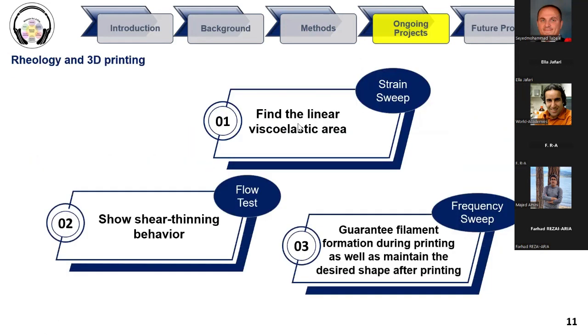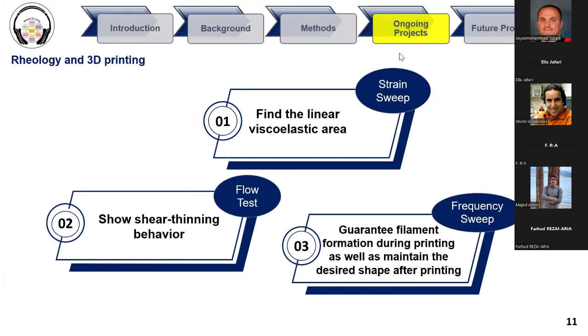But before starting 3D printing, we need to correlate the rheological measurements with 3D printing. This part is so important because before conducting any 3D printing, we need to know the quality of our printing. I mean, whether we are going to have high quality 3D printed shapes or not. So how can we do that? By doing 3 rheology tests, we can make sure that our ink is good or not. First of all, we need to run a strain sweep test to make sure that we are in the linear viscoelastic area, and then we need to run a flow test because for extrusion 3D printing, we need shear thinning behavior. So we need to make sure that our ink is shear thinning.